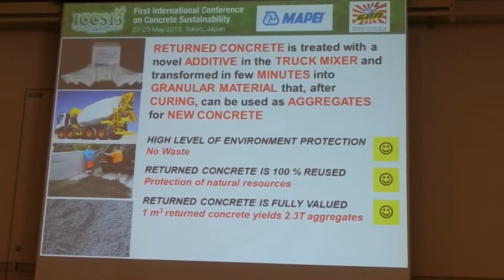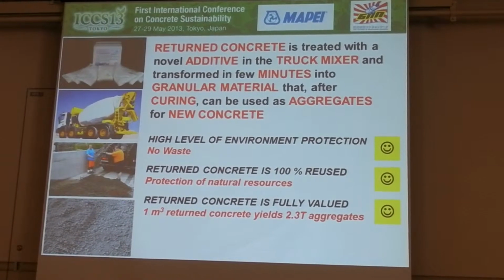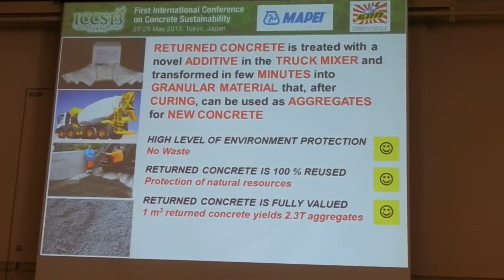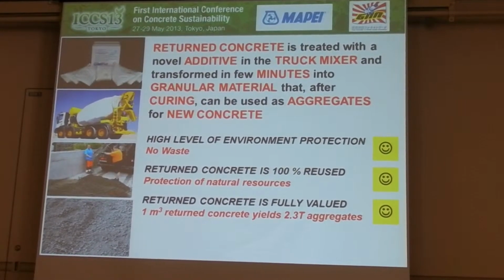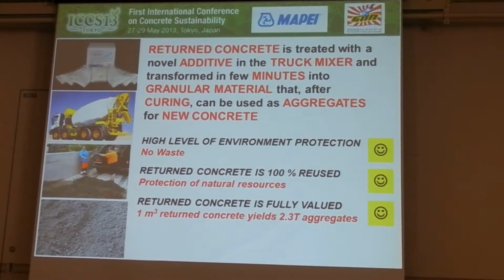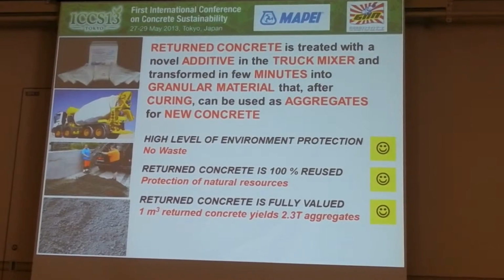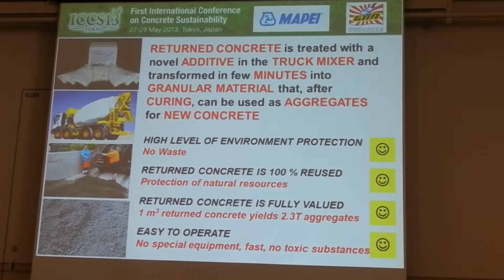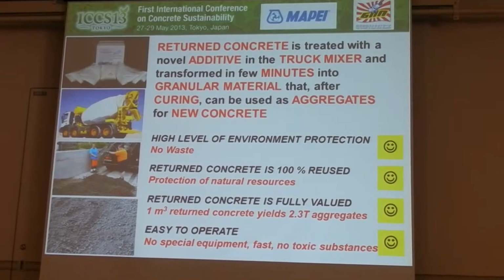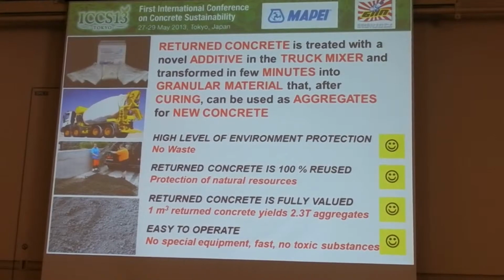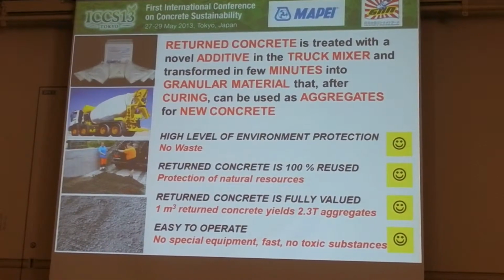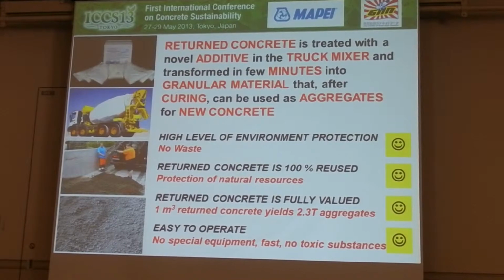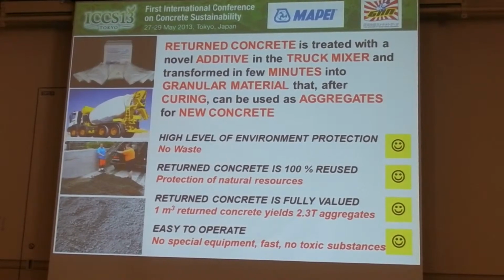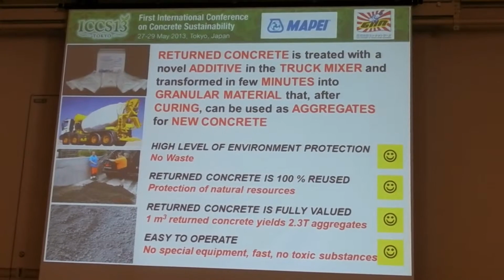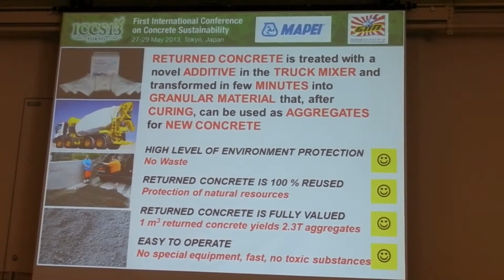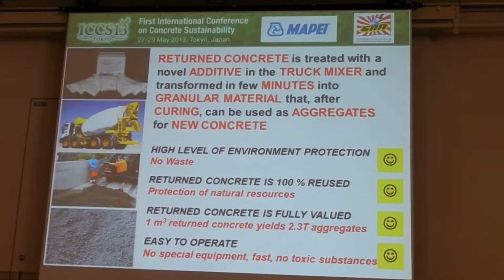Then, from the economical point of view, 1 cubic meter of returnable concrete is transformed in aggregate. This means that about 2.3 tons of aggregate are produced from 1 cubic meter of concrete. And it's very easy to operate because it doesn't require any special equipment, because the process is operated directly inside the truck mixer, and it's very fast. The overall process takes less than 10 minutes, and the additives are not based on dangerous substances or toxic chemicals.